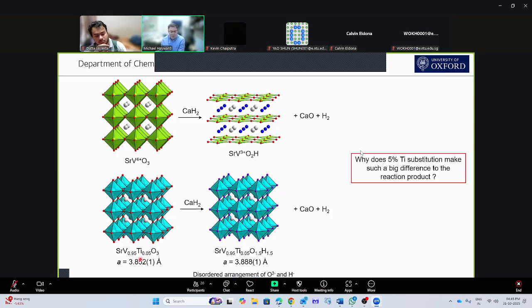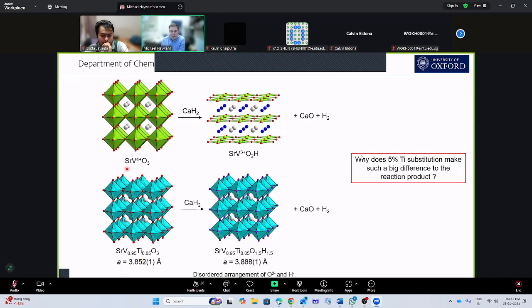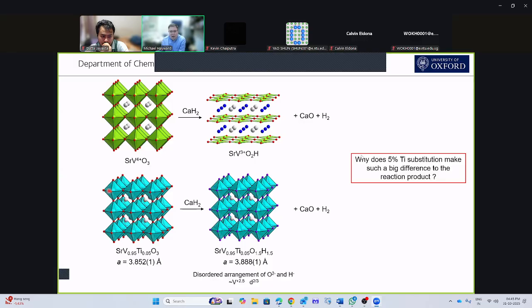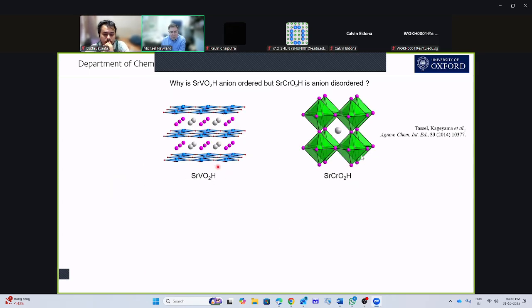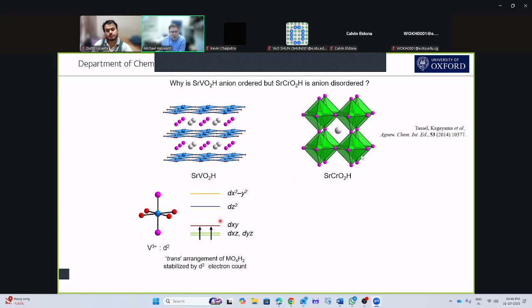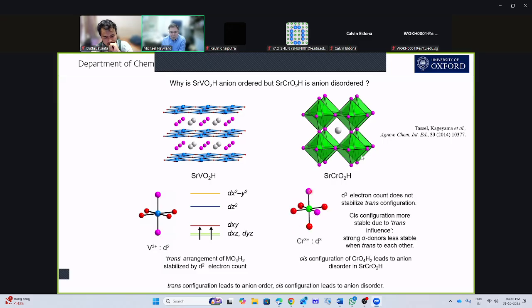So what's going on? Why does 5% substitution make such a big difference to the reaction product? Well, the answer to that can be seen by answering a slightly different question, and this is to look at SrVO2H and its neighboring material SrCrO2H, because what we find is SrVO2H has ordered oxygen and hydrogen, whereas the chromium compound has disordered oxygen and hydrogen. And we can see why that happens, because in the vanadium case, these two d electrons sit in this XZ-YZ orbital, which is stabilized by having the 2 hydride ions trans to each other. But in the chromium case, the 2 hydride ions sit cis to each other, leading to a disordered material.